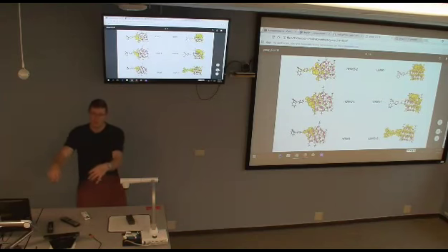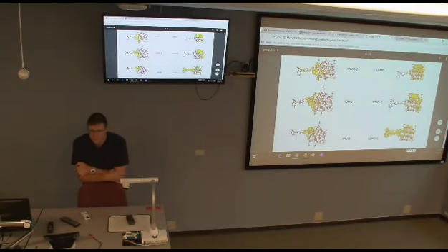So to your deprotonated oxygen, or sulfur, whatever, it goes on a selenium close by. We don't know exactly the mechanism of attachment or the synthesis, but you can assume that they probably have this linkage group protonated, right? And then it's deprotonated either in solution and then comes without the proton, or maybe when it's approaching the surface it loses the proton. This deprotonation happens and the proton might be caught by the selenium.